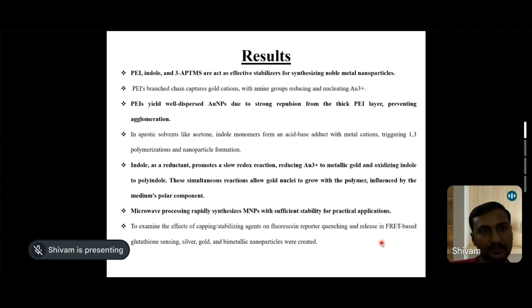Polyethylenimines have a very branched structure, capture gold cation with amine group, followed by reducing and nucleating of gold cation. Further, polyethylenimine yields well-dispersed gold nanoparticles due to strong repulsion. Because polyethylenimine is cationic in nature, it provides overall cationic charge on the stabilized nanoparticle that promotes the strong repulsion between the two nanoparticles and prevents the agglomeration of nanoparticles via forming a thick polyethylenimine layer on the nanoparticle surrounding.